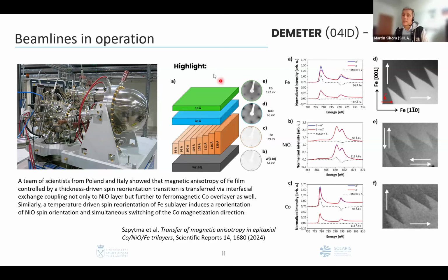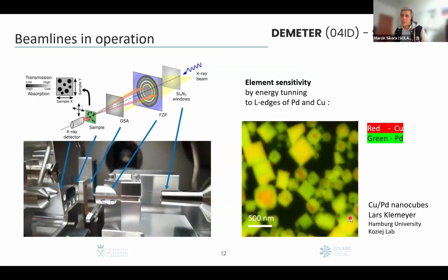And as you can see, this microscope provides you magnetic information with circular dichroism, linear dichroism, but also chemical information, because you can tune to either the nickel edge, you can tune to the iron edge, you can tune to the cobalt edge, and also see the distribution of these different elements in your sample. The other microscope that is operational at this beamline is the so-called scanning transmission X-ray microscopy. So in this case, we have to focus our photons using Fresnel zone plates to a very, very small size, to about 20 to 30 nanometers.